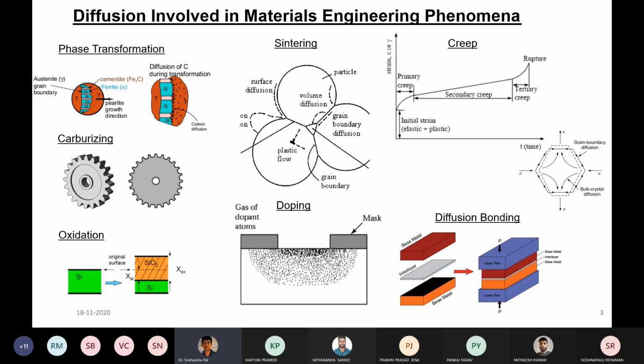And what is it? Carburizing is the addition of carbon to the surface of the low carbon steel at high temperature, generally between 850 and 980 degrees centigrade, at which austenite, with its high solubility for carbon, is the stable crystal structure. So now things are very simple. What we are going to do is reach the austenite phase through a certain temperature, and then incorporate carbon inside the austenite phase of the low carbon steel that is staying at the surface of the product.